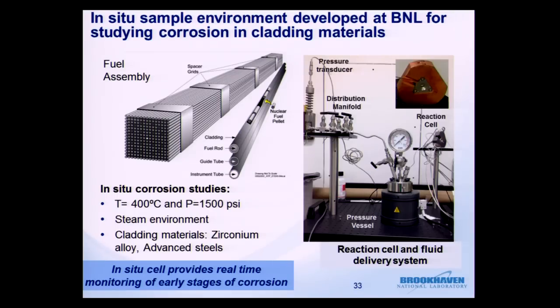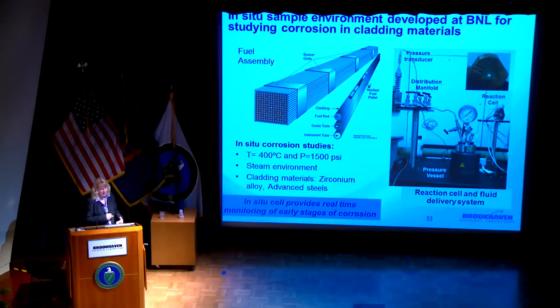This is an in situ cell for studying corrosion at the light source. So this is a heater, and inside there's a small chamber. We're able to take a small piece of this cladding material, put it in the chamber. The chamber has windows that are transparent to X-rays, and we can watch the very initial and early stages of corrosion. This cell is capable of reaching 400 degrees C and providing a corrosion in a steam environment. We've already looked at some zirconium alloys and advanced steels. And with this, we'll be able to do real-time monitoring of the formation of corrosion films.